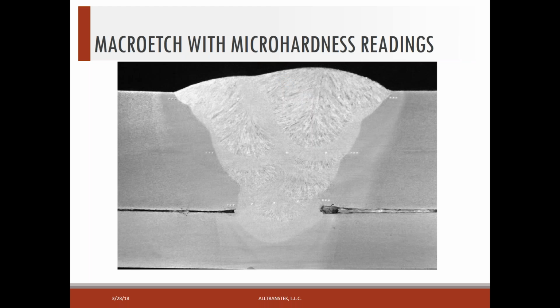Okay, we mentioned macro etch earlier. This is not an example of a partial pen weld. This is a full penetration weld into a backing, and this is the macro etch, and I'm not so sure that you're able to see it, but there are some small dots in 3 areas on that particular specimen, down toward the bottom. You can see it in the heat affected zone and across the weld, and then through the middle of the weld, and then also close to the surface of that weld. Those are micro hardness readings taken by the test lab. So that's an example of what that would look like if you were looking at cross section.